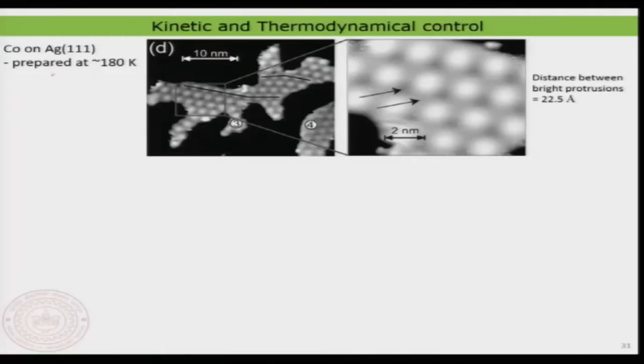So now keep that in mind. We'll get back to the discussion. Now let us look at the other example. That was actually the cobalt prepared at 180 Kelvin. Now something interesting, as I've already told you, the bright protrusions are actually spaced by 22.5 angstrom, that you can precisely measure. And that distance is now exact, very different compared to what is observed in the other case.